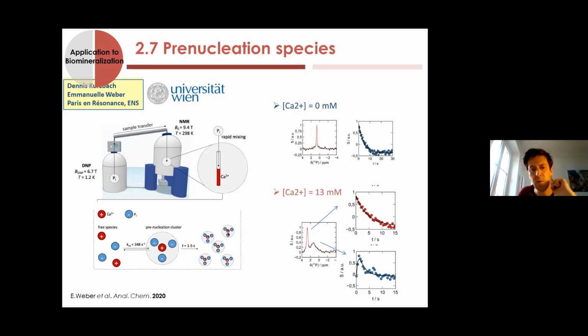What is interesting also is that by measuring other parameters like the line width, you can have access to the constant of exchange between the free phosphates and the phosphate in the prenucleation species, because that species is still solute, and the phosphates are always exchanging with each other.